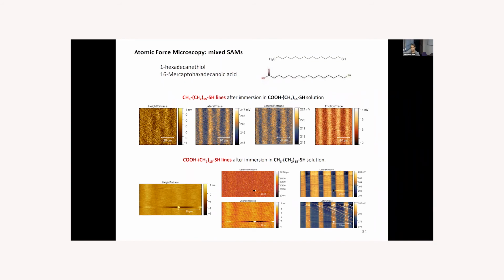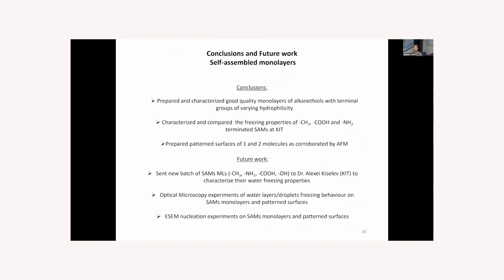For now, we didn't have the occasion to make other experiments such as optical microscopy freezing with ice tip or ICMAB ice growth to see if there is any difference in the freezing of water on the surfaces. So for now, we have prepared and characterized good quality monolayers of alkanethiols with terminal groups of varying hydrophilicity. We characterized and compared the freezing properties of methyl, carboxylic and amino group terminated SAMs at Karlsruhe Institute of Technology. And we also successfully prepared the patterned surfaces of 1 and 2 molecules, as shown just before by AFM.